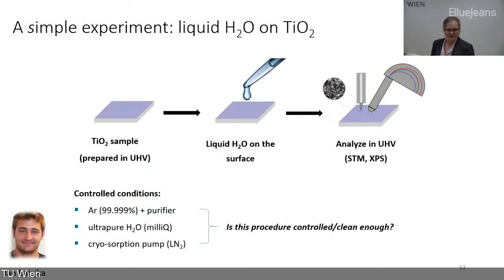One of my former students, Jan Balajka, was trying to do exactly that, because for the TiO2 surface I mentioned before, there were reports in the literature that putting it in liquid water changes it. They cleaned and characterized the surface in ultra-high vacuum, put a drop of water on it with a pipette, then put it back in and looked. It looks like a simple experiment, but he went to great lengths to make it really clean—clean water, clean gas, pumping, and so forth. The question was whether the procedure was controlled and clean enough, and unfortunately the answer is no.